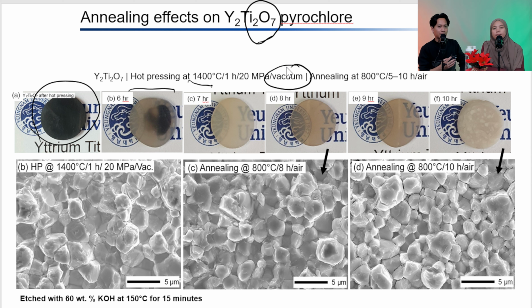The oxygen exits from the lattice, and therefore it is in an oxygen-deficient state. But usually there would be some pores inside, if a gas is vaporized, right? Yeah, but in this case it's not pores, just ions diffusing out from the lattice. So to achieve transparency, I did annealing in air at around 800 degrees Celsius, and you can see the progress.